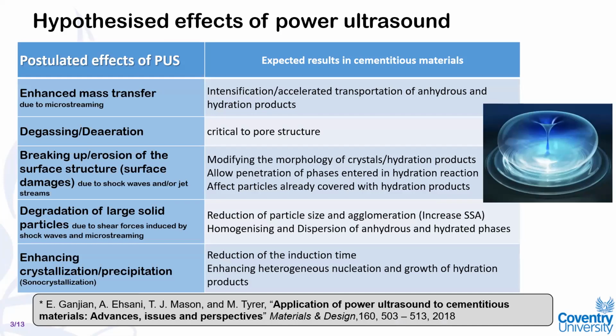In our review, we discussed some effects of power ultrasound in cementitious material: enhanced mass transfer due to microstreaming, degassing and deaeration, which is one of the most significant effects of cavitation phenomena in sonication. Breaking up and erosion of surface structure would be influential on exfoliation of particles in cement hydration. Degradation of large solid particles would be another effect, and enhancing crystallization and precipitation would be another important effect of sonication in cementitious material. We try to trace the indirect evidence of these effects in cementitious material systems due to the application of sonication.